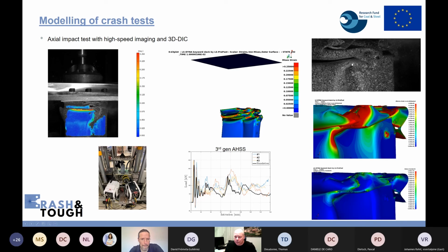And this is one image from this crash box test, and maybe you can see some cracks occur, but you can see the reason for why we are underestimating the properties, because if you look at these other 2 images from the simulation, you can see we have a crack, but that doesn't occur in reality. So that's the reason that we underestimate the properties. And you can also see in this comparison between the 3 experimental boxes and the black one, which is the simulated one, that if you integrate this curve, it will give you a lower value.